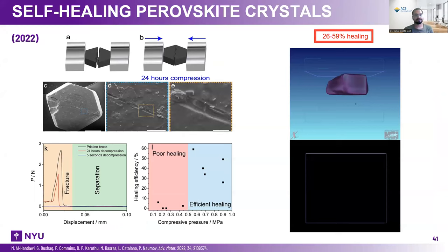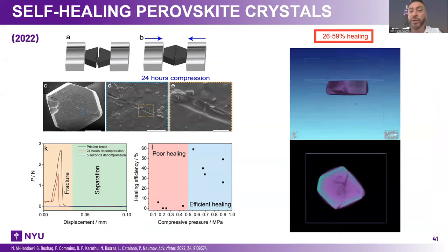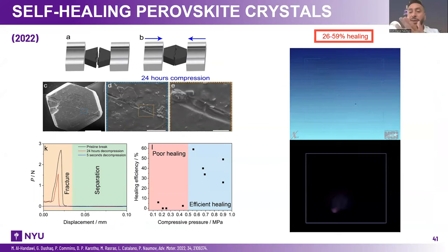So we are interested whether we can apply this concept to self-healing perovskites, because as you know, perovskites are one of the most important materials at the moment for solar cell applications and other applications. And indeed, perovskites can heal. There is evidence published in this paper, but also you can see that we can achieve between 26 and 59% of self-healing in perovskite single crystals. And of course, we have again the CT scan to confirm that, but also plenty of other mechanical tests to prove that. I would like to advise you to check this article, I think it's very important for those who are interested in perovskite chemistry.